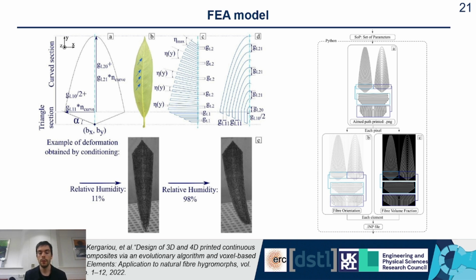We run this model. We also printed the specimen. You can see at the bottom, we conditioned it between 11% relative humidity and 98% relative humidity. Compare the model to the test. We're able to see that there is a bit of difference between the two, and we explain in the paper why we see this difference.